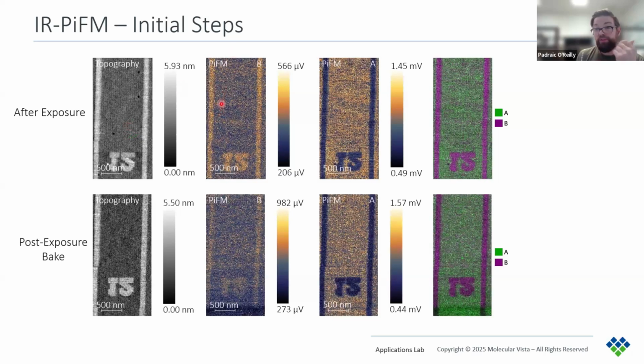So with wave number B, we see highlighted the regions that are taller in topography. So again, this is the unexposed regions. And wave number A highlights the exposed region. In this zoomed out image, it's kind of easier to see what it does not highlight. So this is the unexposed region and these larger lines. But when we zoom in in a moment, it'll be more clear what the exposed regions look like.